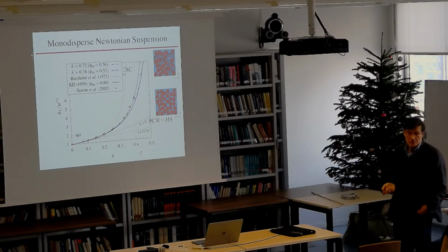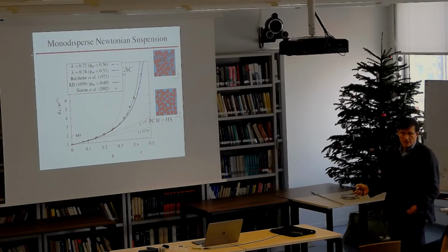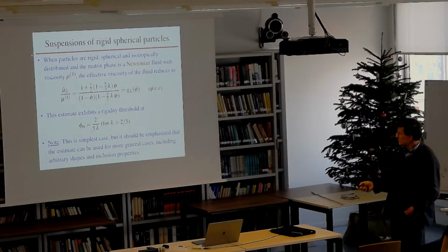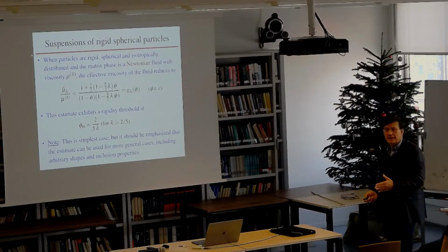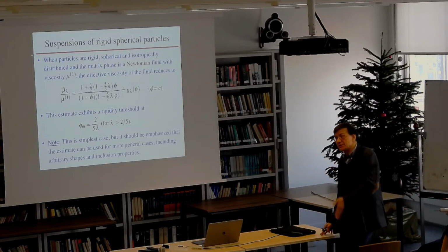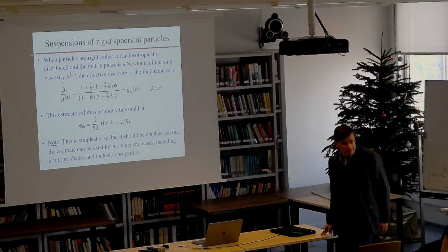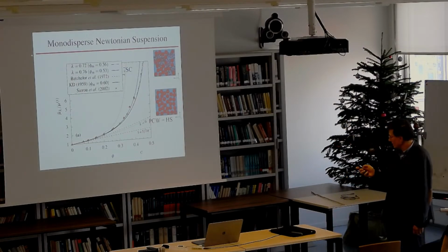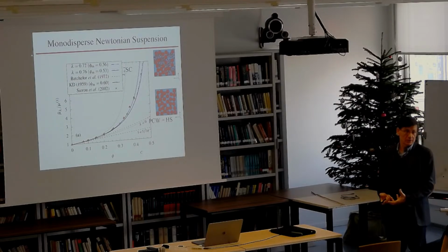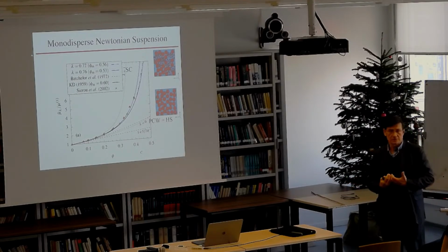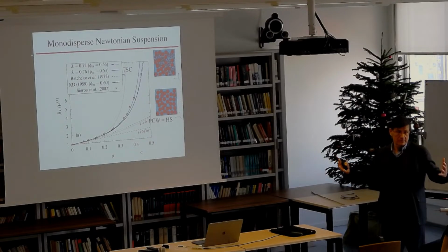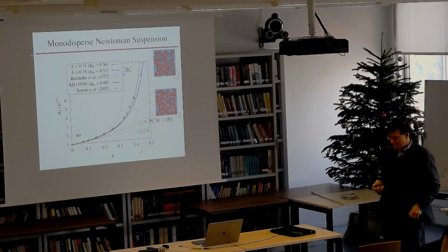So that's one way to try to choose this parameter lambda. Another way is to look at the other extreme, large volume fractions. This method predicts that there is a rigidity threshold, a finite volume fraction where the viscosity or the elasticity blows up. That corresponds to the situation where the particles come into contact with each other, forming these chains.